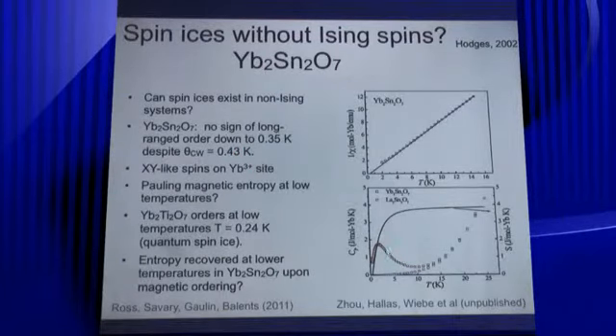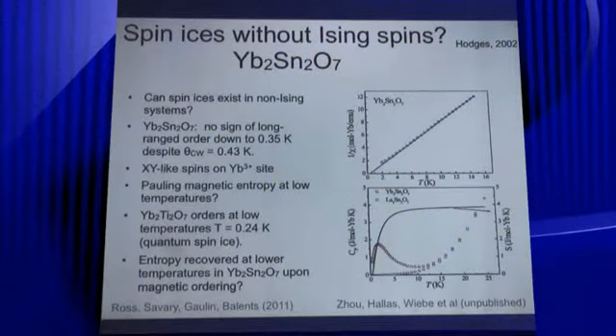And if you measure the heat capacity sort of naively, and compare that to non-magnetic lanthanum stannate, integrate that up, you get something close to spin ice, right? So you may think, oh wow, I discovered a new spin ice. You haven't. So you have to worry about what happens down here, because ytterbium titanate orders at 0.24 Kelvin. We've only measured this down to 0.35.